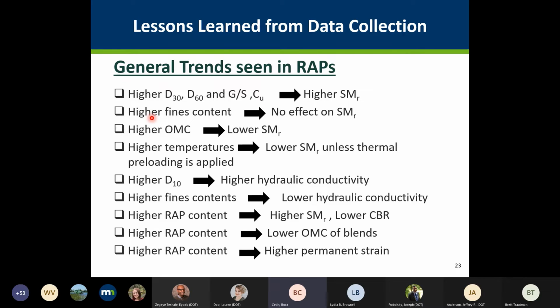So, of course, as expected, OMC here represents the optimum moisture content. The higher optimum moisture content, as expected, resulted in lower resilient modulus values. And the temperature was an issue with the recycled asphalt pavement materials. With higher temperatures, of course, because asphalt binders still exist in these materials, higher temperatures resulted in lower resilient modulus values, unless there are some thermal preloadings.